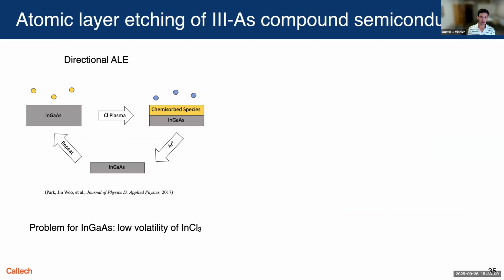So today I want to tell you about an approach that's getting a lot of interest in both nitride and indium phosphide communities, and that's atomic layer etching. And the idea is that rather than having a continuous etch, like what I showed on the previous slide, you instead break the etch up into steps, where each step intrinsically does not etch. But when you combine them together in a cycle, they do etch.